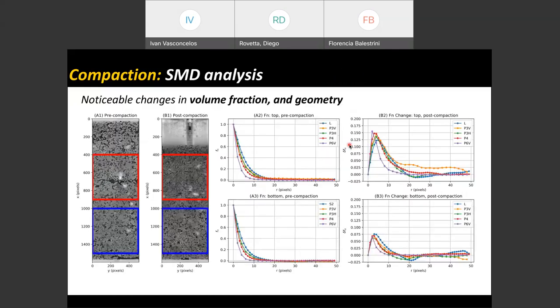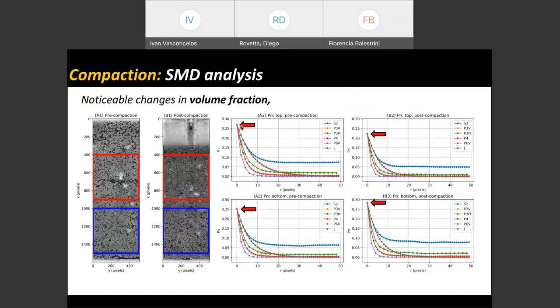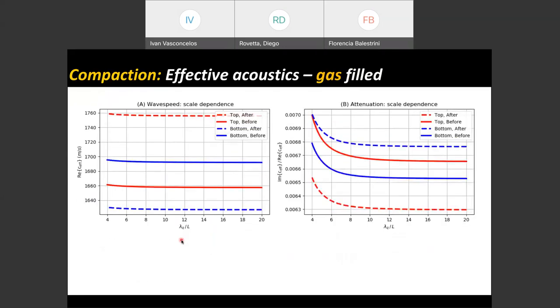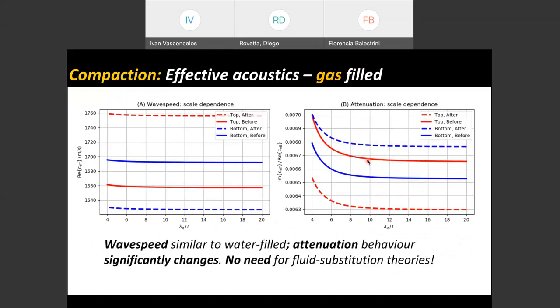So now I'll go back up some few slides. Notice that the top before had a certain value of porosity. Top after is close to that value. So this here and that here have similar porosity, but notice that the geometry of the pores is very different. So you can see right here that they start at similar values of scattering attenuation, and they slowly taper to different values because the geometry of the pores is different. So right here, we can see that attenuation behavior significantly changes when we change the content of the pores. And this significant change also carries information about the change in the geometry.